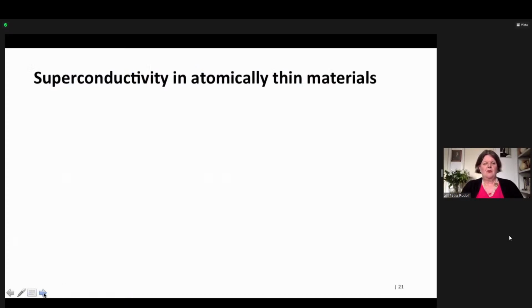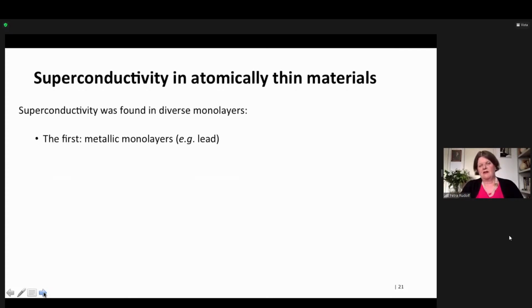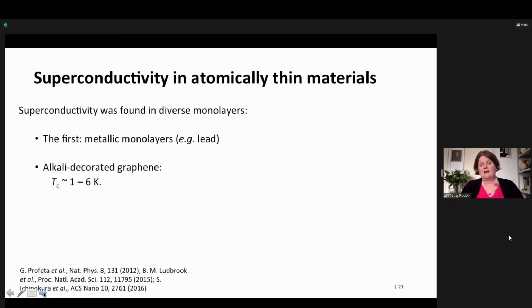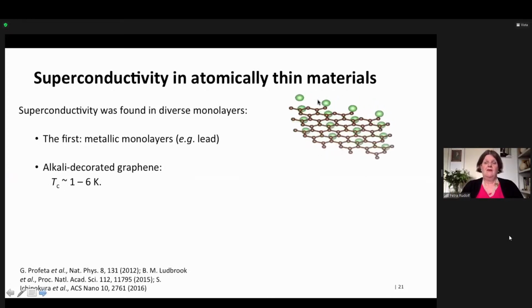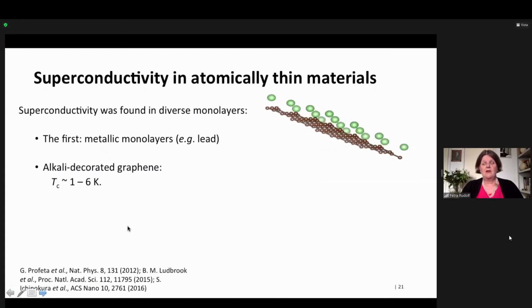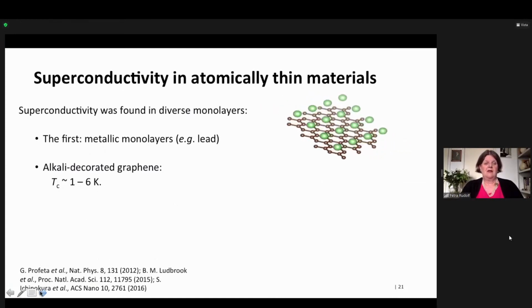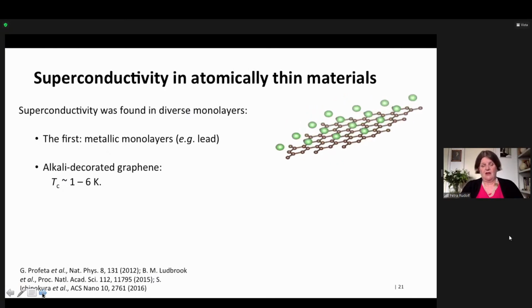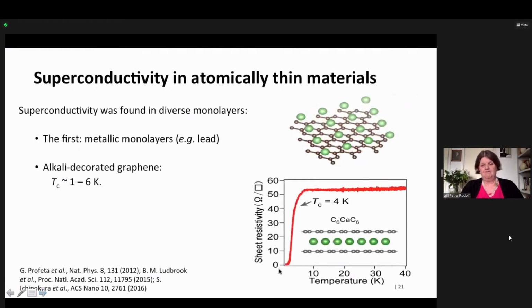Now I want you to think of something completely different, namely superconductivity. You know that superconductivity has been found in several very thin materials. The first was metallic monolayers, lead, and then there was alkali decorated graphene. And if you look at it, this is what it looks like. The critical temperature is very low, but there is no doubt that it becomes superconducting.